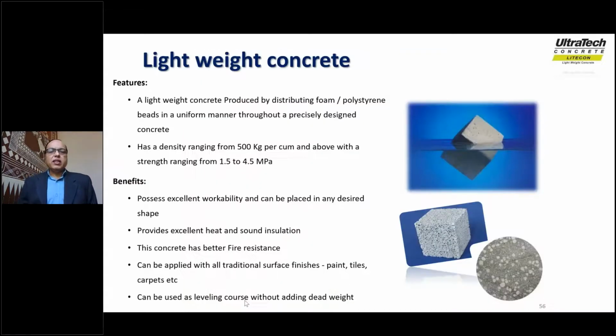The next variety of concrete that I am going to deal with is lightweight concrete. As I said earlier, like foam concrete, lightweight concrete is also a low density concrete. In this case, it is not produced the way foam concrete is produced. Its weight is reduced by using either foam or polystyrene beads. Using polystyrene beads also reduces the requirement of coarse aggregates. Therefore, it reduces the density of concrete also. You can bring down the density of concrete to about 500 kg per cubic meter. But then the strength also would be in the range of 4 to 5 MPa.